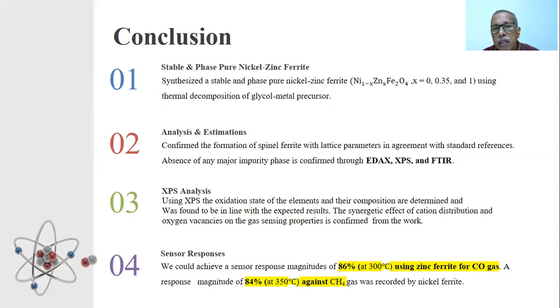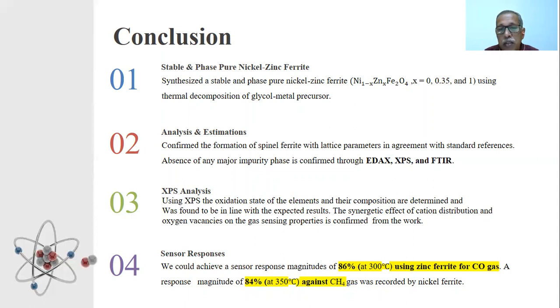The conclusion is that using thermal decomposition of glycol metal residue, it is possible to synthesize spinel structure ferrite material. The phase purity is confirmed using EDAX, XPS, and FTIR analysis. Oxygen deficiency and existence of more than one oxidation state of the cation are confirmed in the XPS analysis. The material shows significant gas sensing features when it is kept at the appropriate operating temperature and against the gases used for the study.